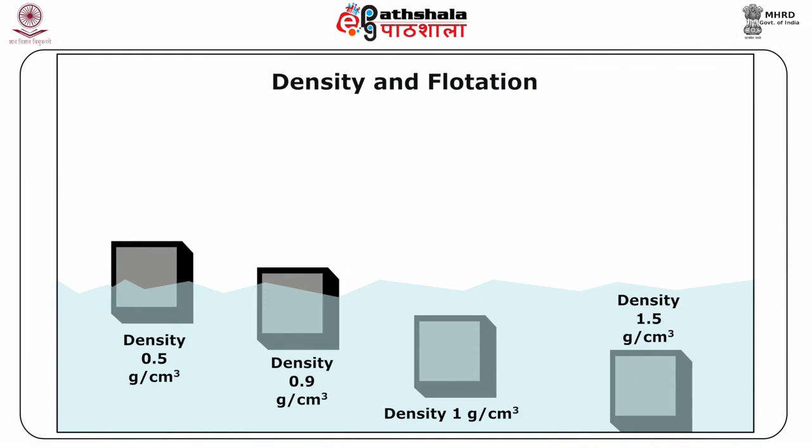The glass will float on the liquid surface. This indicates that the density of the liquid is greater than that of the glass. Then slowly add the less dense liquid, bromobenzene, dropwise with stirring until the particle is exactly suspended. If the addition of bromobenzene is in excess, which is indicated by the sinking of the glass particle, then bromoform is added until the glass chip remains suspended in the liquid medium. Care is taken to see that the mixture is stirred with each addition and the air bubbles, if any, are removed. Now add a similar size, clean and dry sample of control glass.